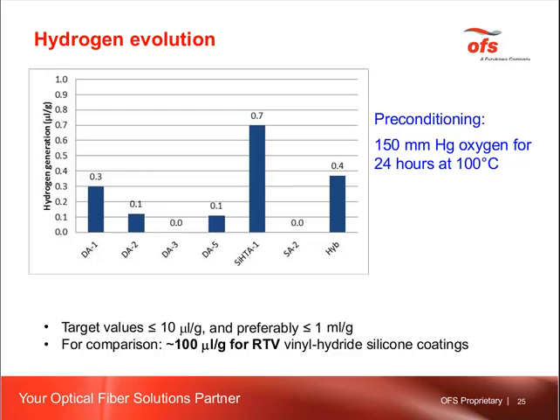And at the bottom of this slide, you can see the number. 100 microliters per gram, milliliters per gram is typically evolved from RTV type coating. So all these fibers can be considered as evolving just a little hydrogen, and this shouldn't be a problem. And for two of the coatings, we see that even no hydrogen was generated during the testing.